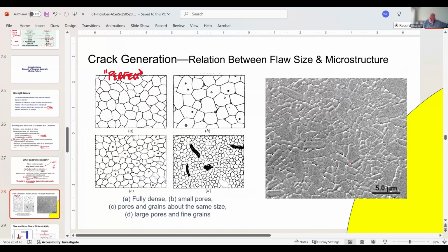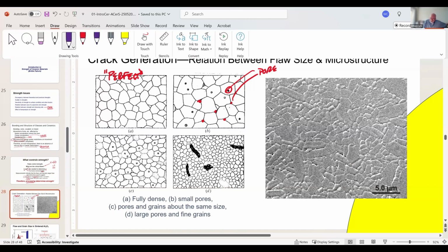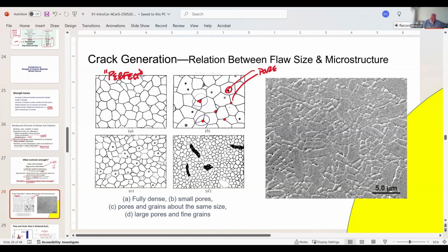Okay. And then you have one that has some defects, and you can see the defects in here. And these are defects that are pores. This is a pore here. These are also pores. These pores that are inside the grains tend to be unimportant. The ones in the grain boundaries, which I'll make purple or whatever, these grain boundary pores are more important in terms of strength control.